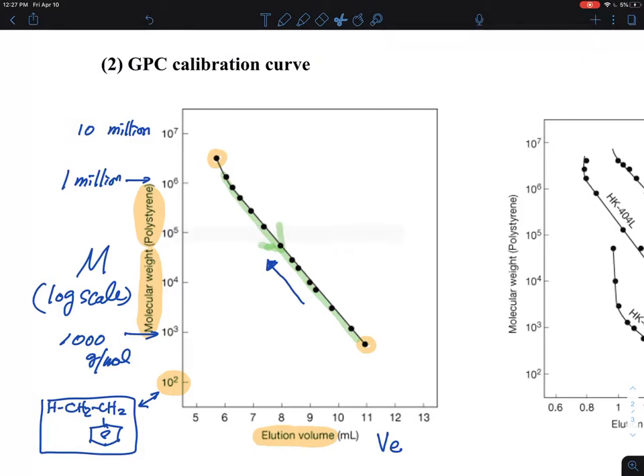I'm just here assuming the constant flow rate is about 1 milliliter per minute. So I'm kind of using this milliliter interchangeably here. But elution volume is a result of elution time multiplied by volumetric flow rate. And so if you have an analysis on this, it is kind of curving up, and it will lose your kind of resolution at the end.